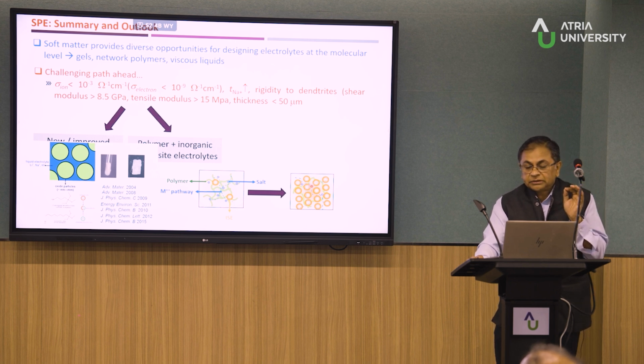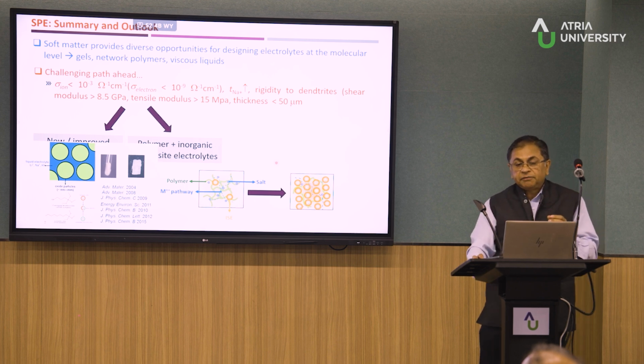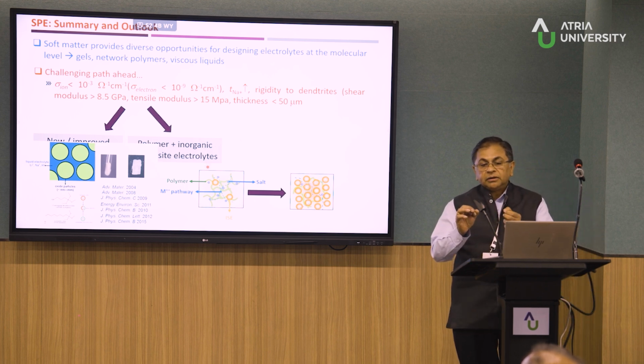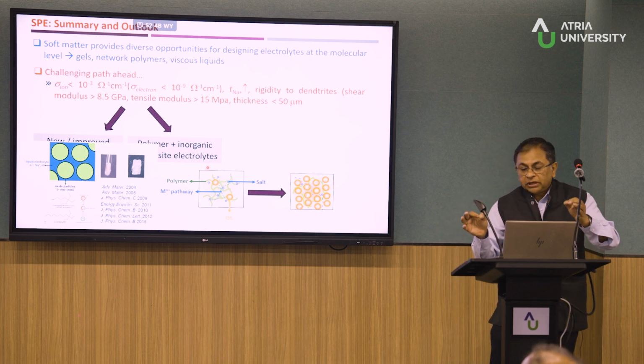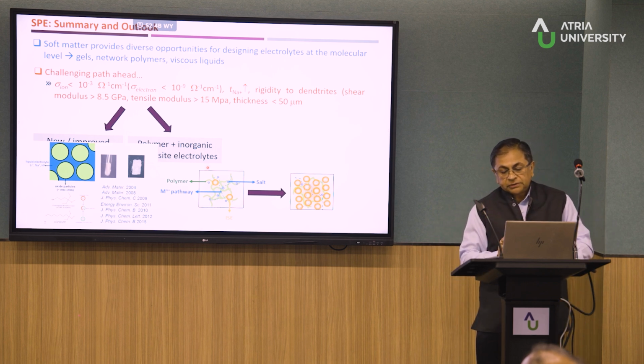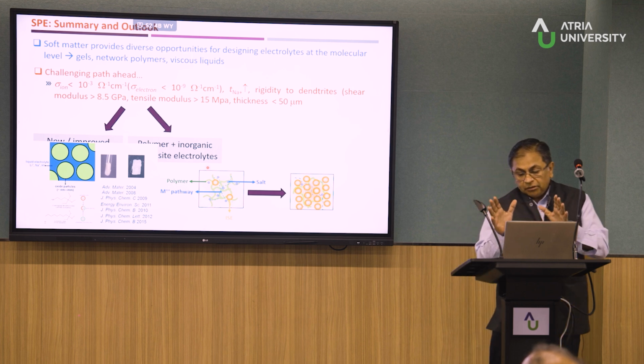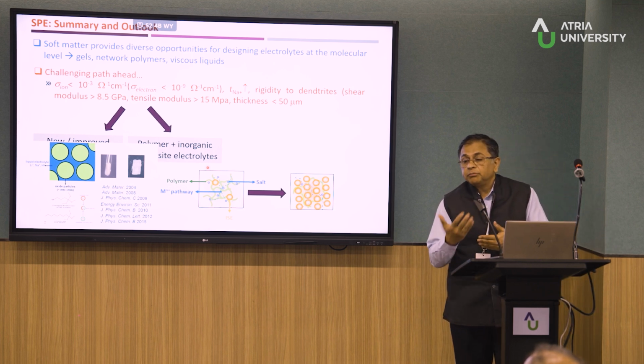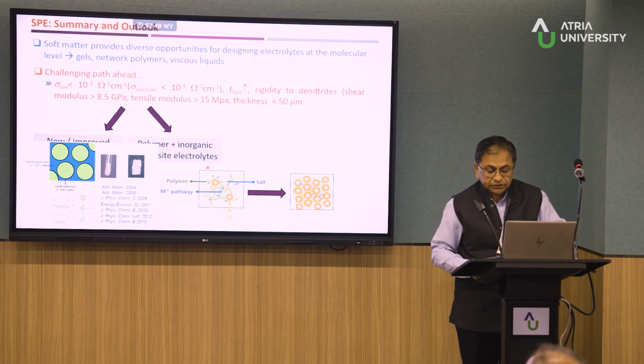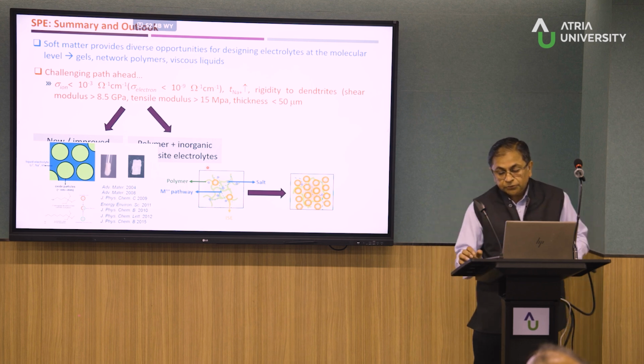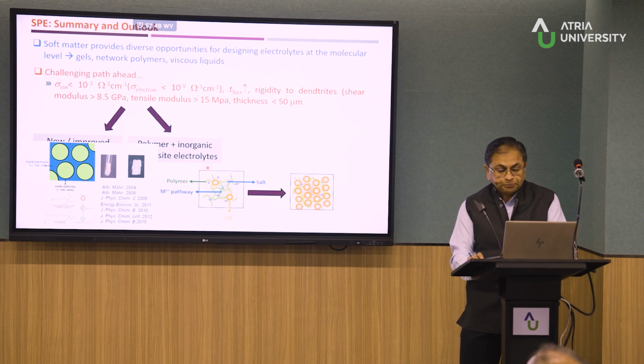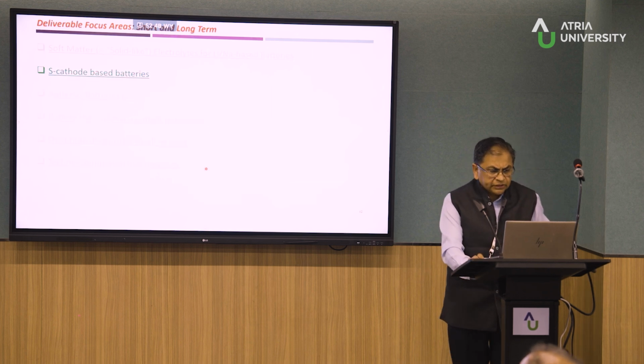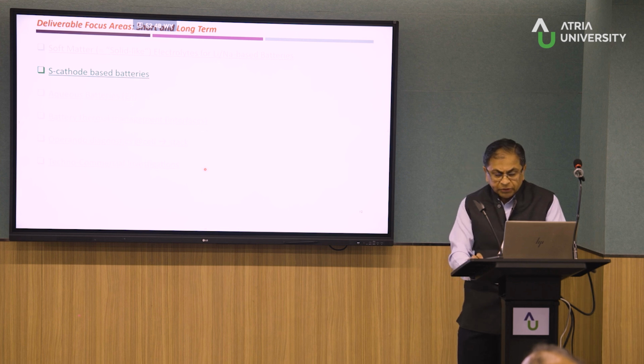the filler content should be the majority fraction. Okay, so in this way, what the polymer does is act as a binding element, or a binding conduit between the various solid electrolyte particles, which is going to give you a conductivity matching that of a solid electrolyte, but with much better adhesivity and much better interface, which will lead you to a high-performing battery system.